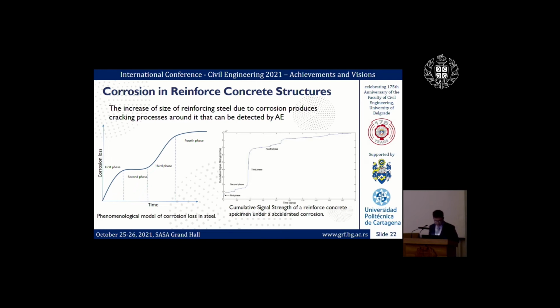Here we have a phenomenological model of how the corrosion loss occurs in steel, with 4 phases, depending on the corrosion properties in each part. And it has been found that using a parameter from acoustic emission, the signal strength, the cumulative signal strength follows a similar pattern, which indicates that this technique can be used to monitor the corrosion in this kind of structure.